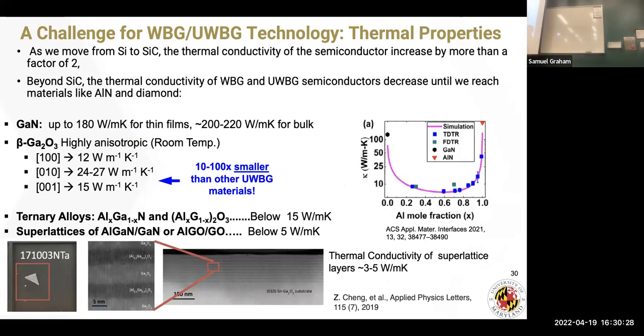When I look at gallium nitride, the thermal conductivity for the thin film form is about 180 watts per meter K. When I go to bulk, I'm around 200 to 220. Now look at the numbers if I go to beta gallium oxide. We're talking about 12, and it's anisotropic: 12, 24 to 27, and 15. So this is an order of magnitude lower. And then if I go to aluminum gallium nitride, it will depend on the amount of aluminum that I have in the material, and so you get this bathtub curve right here. What you're seeing is that this is dipping below 10 watts per meter K. So this is actually worse than beta gallium oxide.